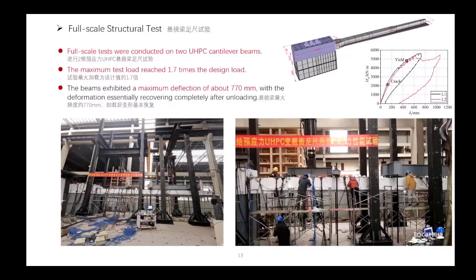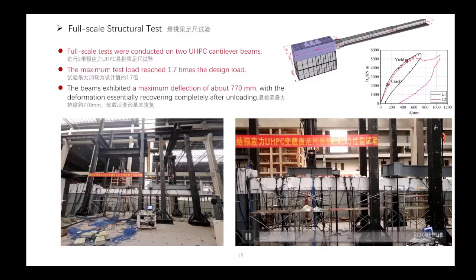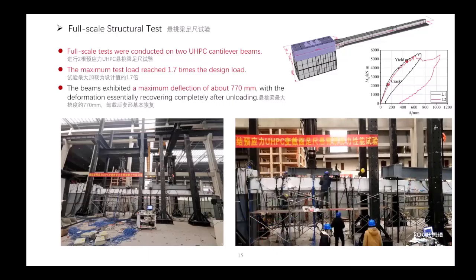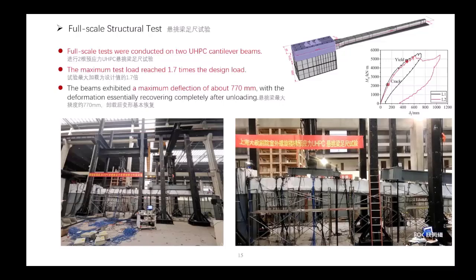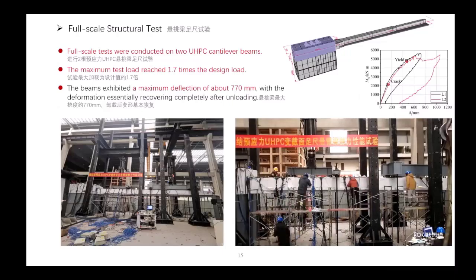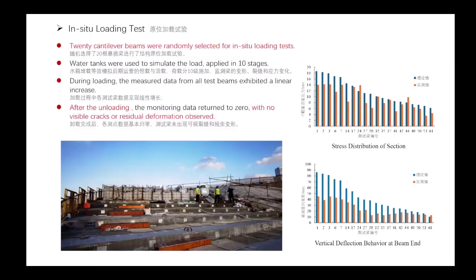Full-scale tests were conducted on 2 UHPC cantilever beams, and the maximum test load reached 1.7 times the design load, and the maximum deflection is about 770 millimeters. This is a test. 20 cantilever beams were randomly selected for in situ loading test. After the unloading, no visible cracks or residual deformation were observed on the beams.